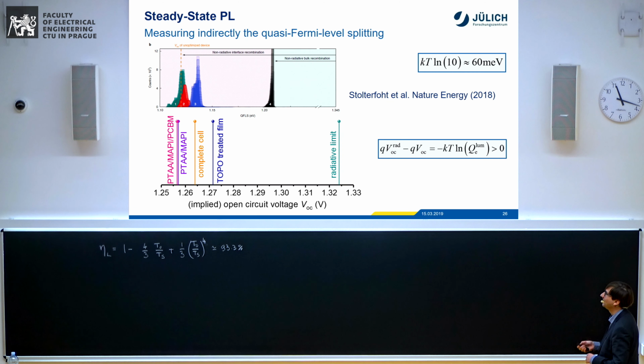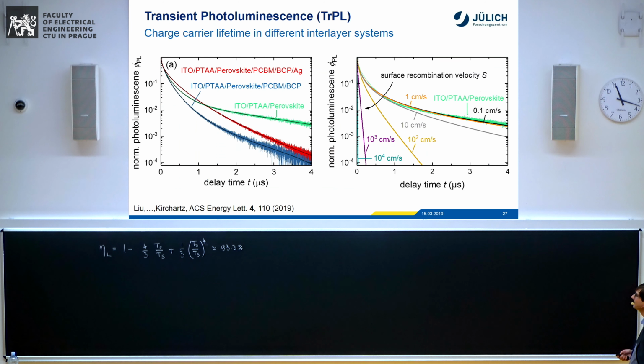And then the complete cell is already the next that we get. And there's basically no difference between 1 contact, 2 contacts, or the complete cell. Luminescence is basically the same. Yeah? So that's quite different to their study. So there doesn't seem to be any strong loss of open circuit voltage due to the interfaces.